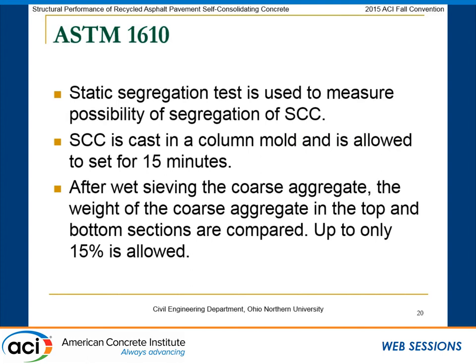And then to validate the VSI, which is very subjective, we did the ASTM C1610. This is a static segregation test. You cast a column of concrete and let it sit for 15 minutes. This column has three sections. After it sits for 15 minutes, you take the top and the bottom section.